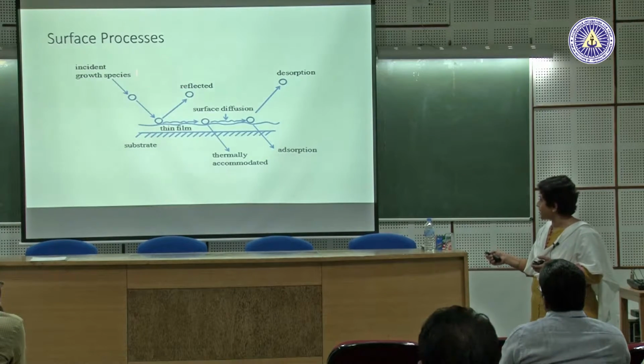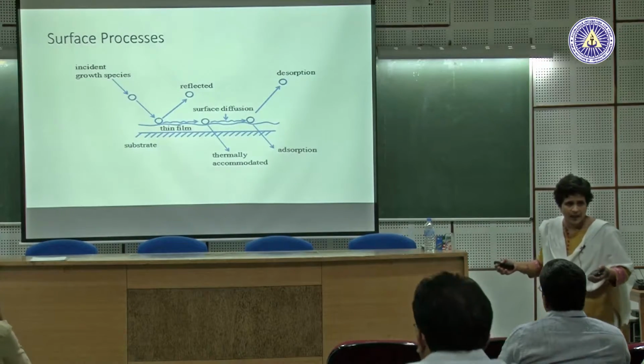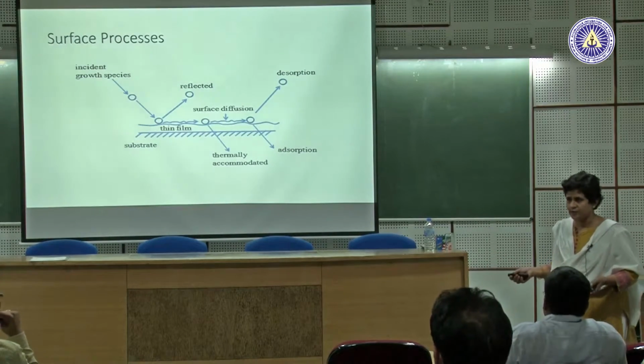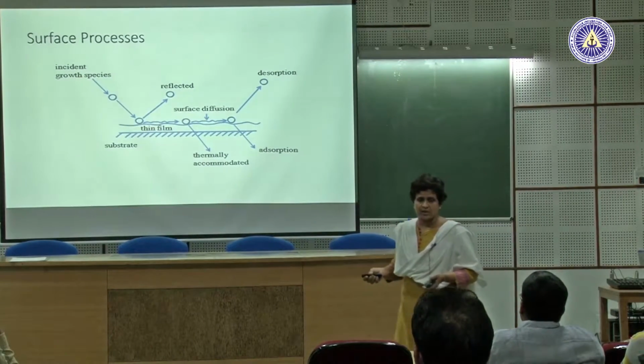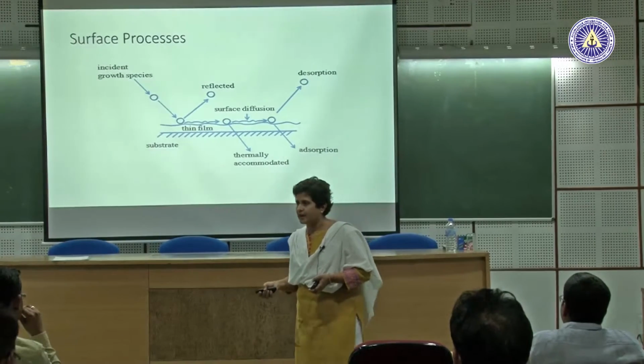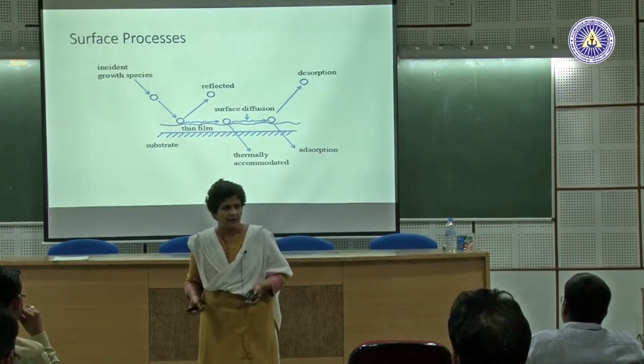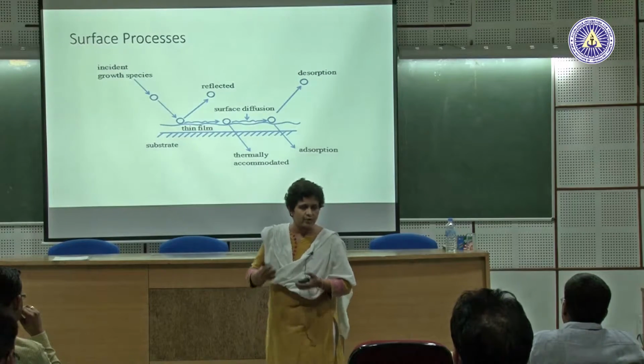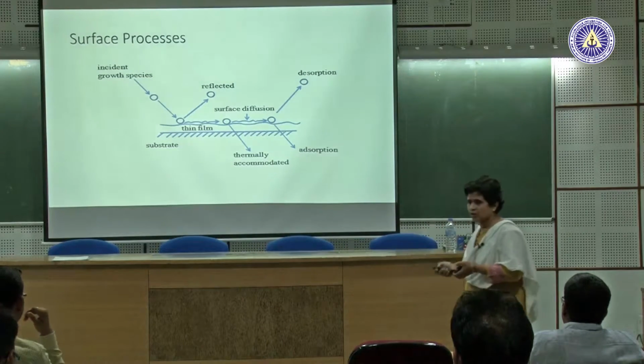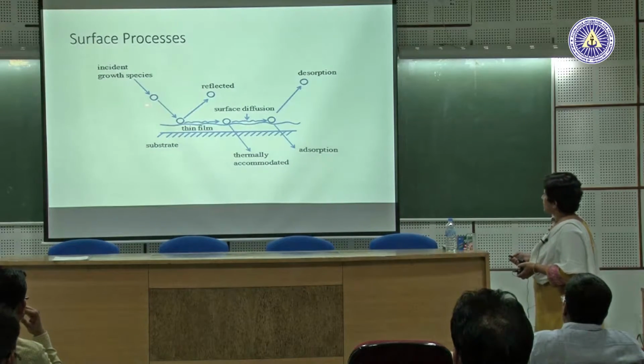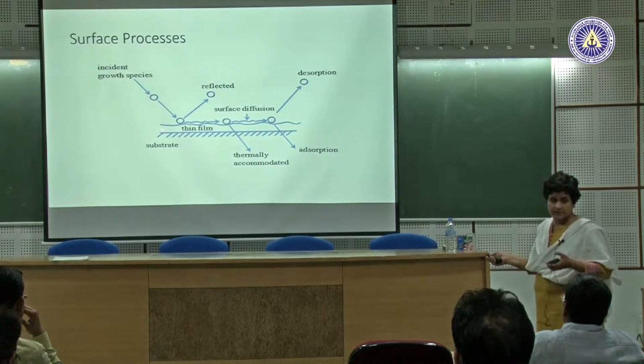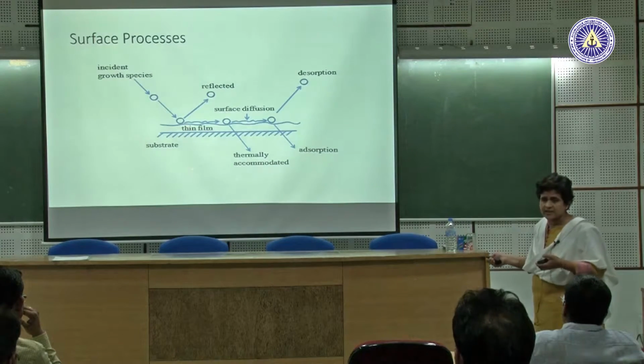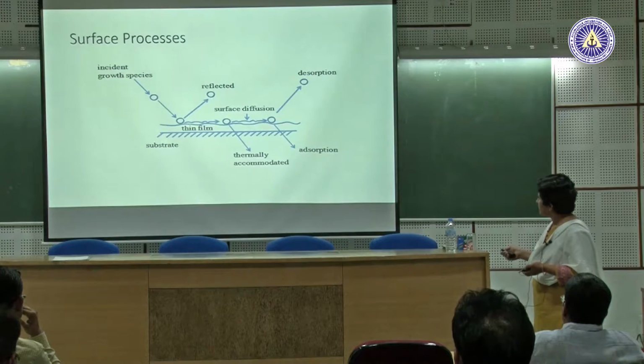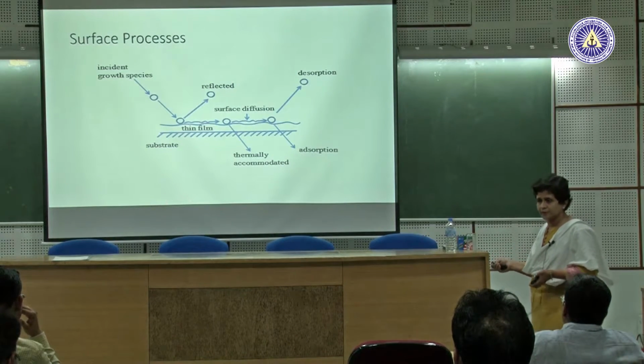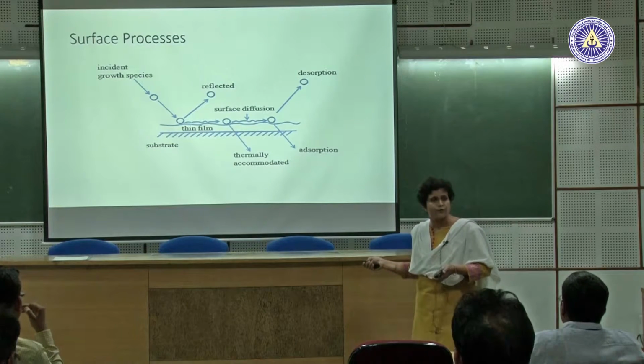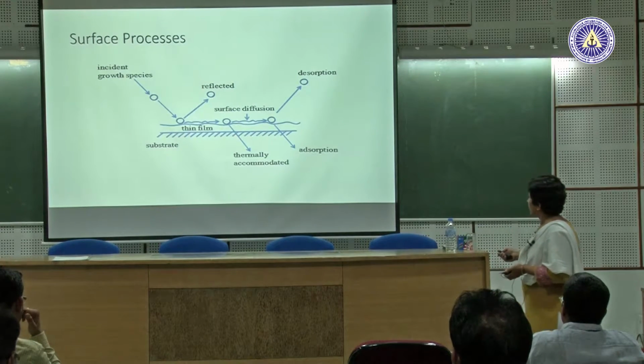And if this good chance becomes 100%, you can evaporate as much as you want, nothing will form. This happens very often. If any of you have done thermal evaporation, sometimes you try to deposit gold on a glass slide, it evaporates, it goes everywhere, but on the glass slide there is nothing, right. So all of it is either reflected or it does not become part of the film. The other possibility is that it does not get reflected, it stays on the surface, but it still has energy higher than the equilibrium energy of the film. So it is diffusing on the surface, and we know surface diffusion is faster than bulk diffusion. It can diffuse on the surface at a much faster rate, and then it has many options.